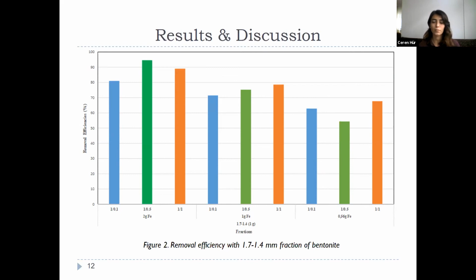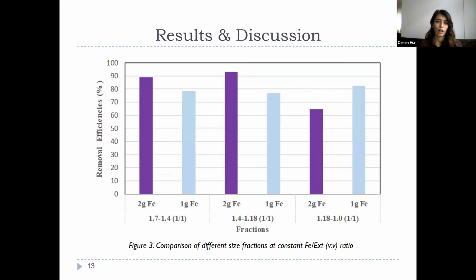Black color has not been observed with 0.56 grams. As can be seen, iron per green tea volumetric ratio does not seem to be a significant factor in terms of phosphate removal. And the last figure shows the effects of different fractions, iron masses, and constant volumetric ratio. There is not a significant difference among size fractions.